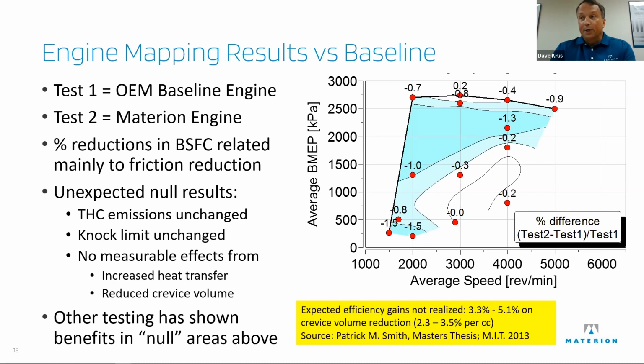But the hydrocarbon emissions just didn't change appreciably. So that meant that the bowl design and the injection profile that Ford has refined for a long time was pretty darn good, because they're probably not getting much fuel into the crevice. So reducing the crevice volume doesn't help that much. We know it helps in other places, so it's still worth doing and proving. And no change to the knock limit.